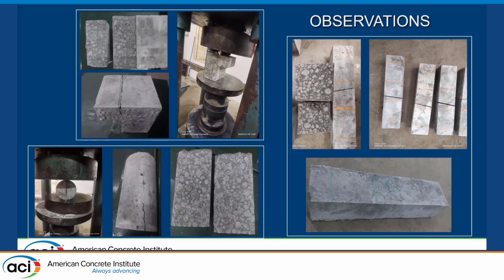Now you can see the first figure shows the split tensile strength test. The very first figure shows the conventional concrete, without fiber reinforcement. We can see a proper failure. But in the picture below it, there's a hairline crack, but it is not fully broken, which shows the fiber imparted ductility and also improved the strength of our sample.